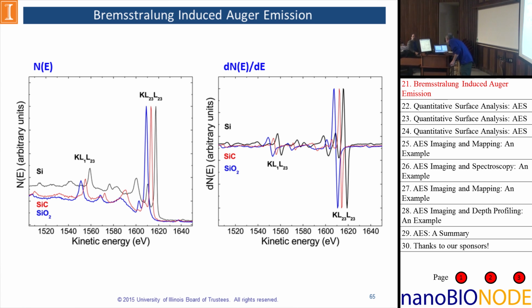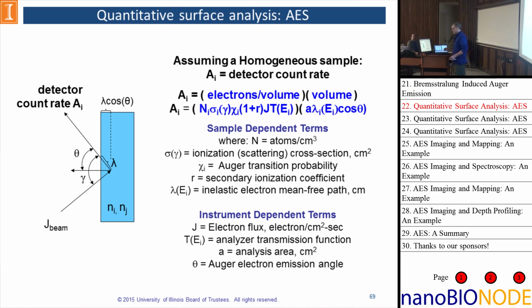I'm going to skip to here. Okay, and so like XPS, you'd like to be able to relate the signal to the quantity of species that are within the material. And you'll get an equation with Auger that's similar to the form of the equation we've seen for XPS, with the addition of two other parameters: the ionization or scattering cross-section for the incident electron, and the Auger transition probability, and the secondary ionization coefficient.